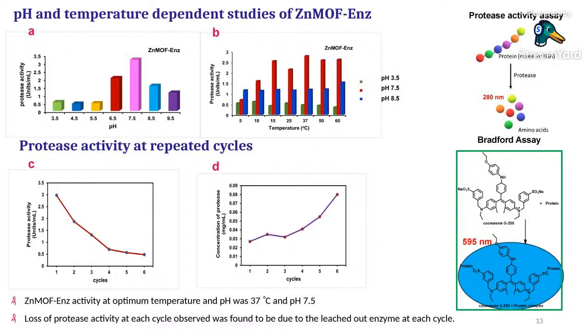And what we did is immobilize the enzyme on the metal organic framework. Most of the time, leather processing is done in a drum, so we mimicked the system in a similar way, with vortexing. We shook it for about 3 to 4 hours. Then we looked at whether the enzyme is leaching out during the cycle. What we found is, yes, there is a decrease in the activity, and we measured how much protease concentration is leaching out in each cycle.